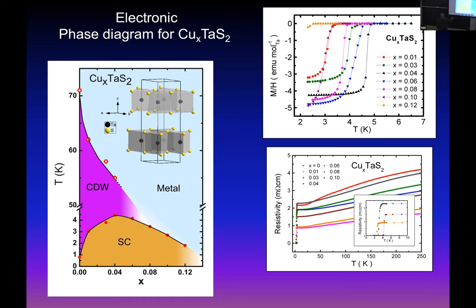When it does that, you can suppress the charge density wave and eventually get superconductivity. So this is what we call a superconducting dome, which is that as you suppress the normal state of the electrons, you can get superconductivity to appear in a lot of cases, in some cases by doping. So putting an atom in there that's going to give up its electrons for the rest of the crystal structure. It's an interesting part of the crystal structure.